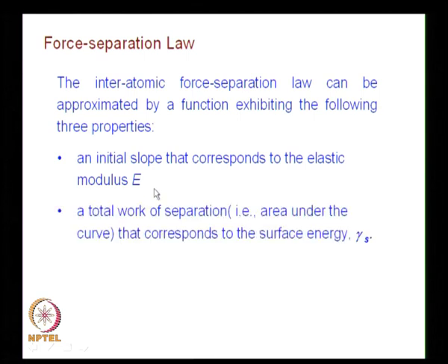And the second aspect is the total work of separation, that is the area under the curve, corresponds to the surface energy gamma s. So, people who are making theoretical calculation have already brought in the role of surface energy in some other form. So, this kind of thinking was there at that time.